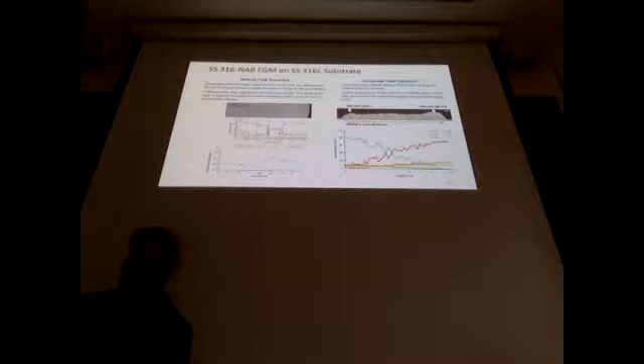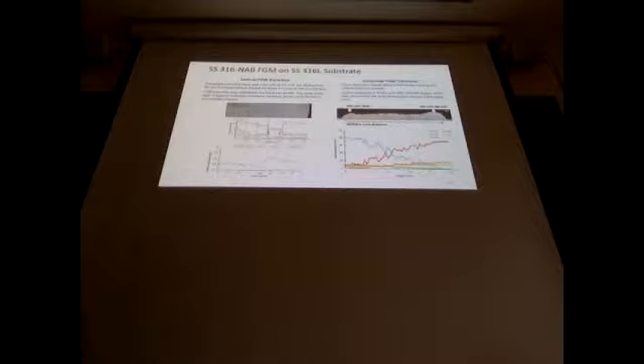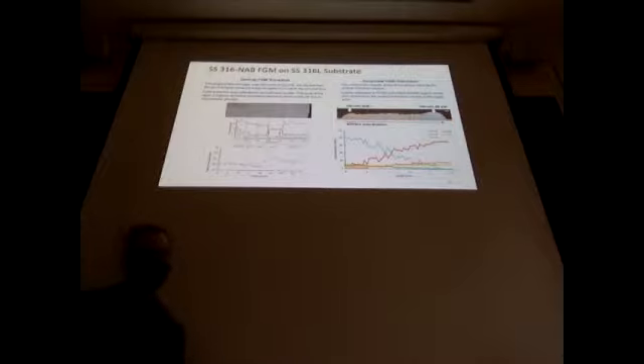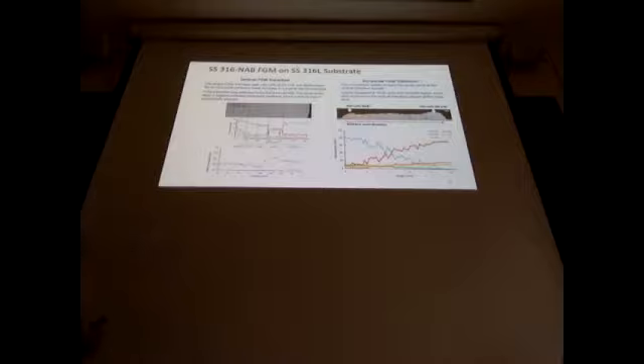And so we built two test cases. There's no reason to do 316 with this; this is NAB, a nickel aluminum bronze alloy. So it's a copper containing alloy with nickel and aluminum, and we're trying to grade it with a 316 stainless, which is mainly iron and chromium. And so we did two types of builds.